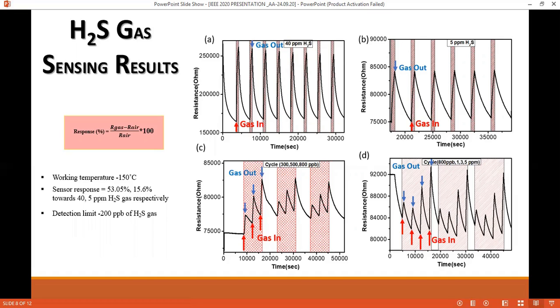In graphs C and D, the sensor was tested at 3 and 4 different concentrations of H2S at a constant operating temperature of 150 degrees Celsius. For this measurement, a diluted mixture of H2S in dry air was injected for 10 minutes in steps of increasing concentrations from 300 to 800 ppb in case of graph C and from 800 ppb to 5 ppm in case of graph D.